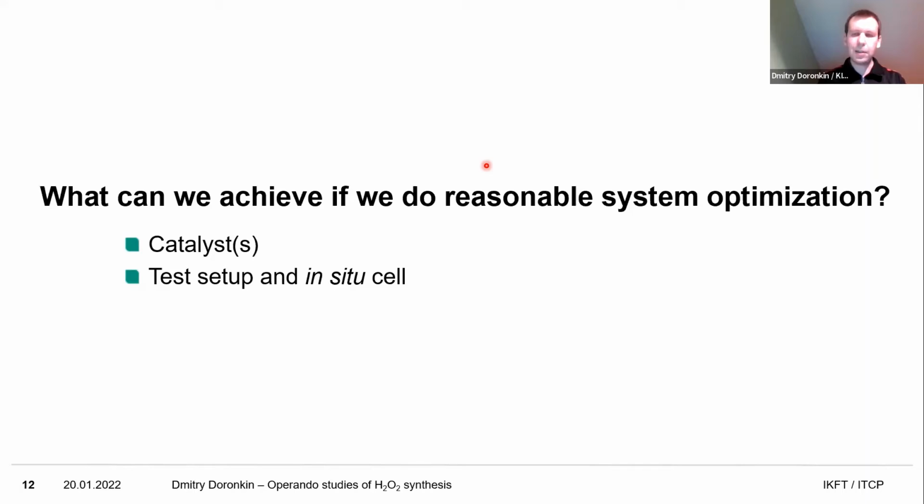Yes, and that's what we did to evaluate the oxygen coverage. So we had the amount of change, basically, of a fraction of the oxidized palladium, and then we related it to the size of the nanoparticles, and it corresponded very well.